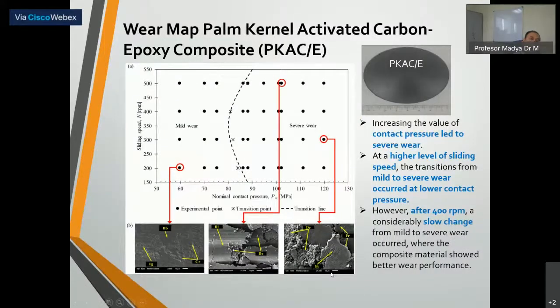Okay, this is the wear map for the palm kernel activated carbon composite. This wear map is a function of contact pressure and sliding speed. Increasing the value of the contact pressure leads to severe wear. At a higher level of sliding speed, the transition from mild to severe wear occurs at lower contact pressure.